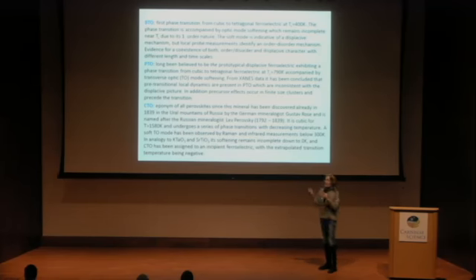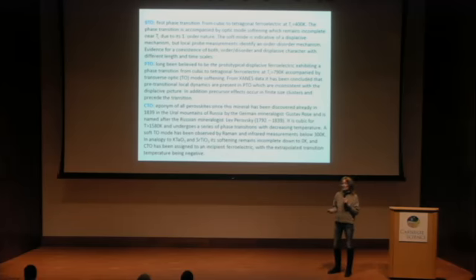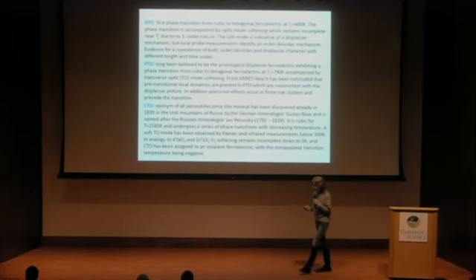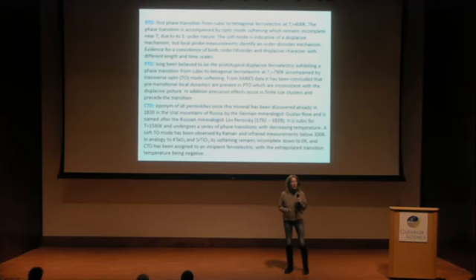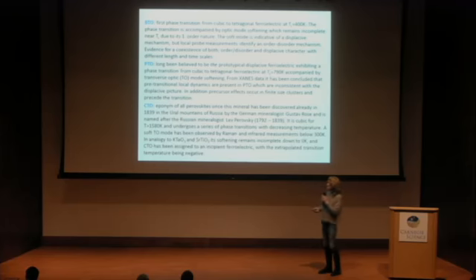So barium titanate is, as everybody knows, a ferroelectric below approximately 400 K. It has long been debated whether it is an order-disorder or displacive ferroelectric, because there's a soft mode, a transverse optic soft mode, but simultaneously local dynamics shows that there must be some order-disorder component. And there were recently a couple of papers which showed that you have a coexistence of order-disorder and displacive character. PTO has long been believed to be the classical soft-mode-driven displacive ferroelectric, but again recently XAFS and SANS results, NMR and all these local tools showed that there's also an order-disorder component in this crystal.